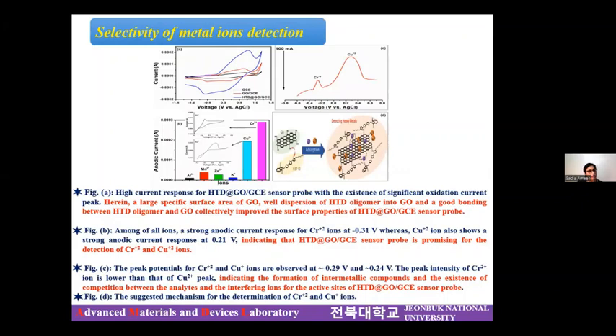And you can see that it shows a very promising redox reaction with promising oxidation as well as reduction peaks. And since we wanted to perform it for the detection of heavy metal ions, we incorporated several heavy metal ions into the solution, and we found that our sensor is promising for detecting chromium and copper as compared to the other incorporated heavy metal ions. And one more thing, we obtained a lower peak for the chromium ion as compared to the copper ion. That might be due to the formation of intermetallic compounds and the existence of competition between the analyte and the interfering ions for the active sites.